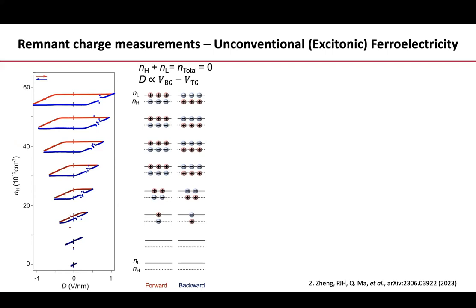It's not as simple as that because you may wonder, wait a moment. I mean, if you just did this, you should undo this. But no, the moment I add this other carrier to the system, there is an exciton formation process, which is a many body state. To get the ferroelectricity, to get the hysteresis, there must be some rigidity in the system, yeah? To not just simply undo what you just did, the system has to change in between when you added that. And that is the formation of the ferroelectric, okay?